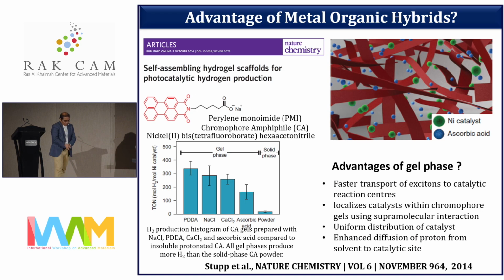So this is the first paper by Samuel Stupp's group, which really asked our group to think differently. This is the perylene chromophore, connected to amphiphile-type molecules, with a hydrophilic head and the pi chromophore. When it self-assembles, it forms a supramolecular polymer, and eventually crosslinks to form a gel. This acts as the light harvesting moiety, and when connected this way, the exciton migration is very efficient, enabling faster transport of the exciton to the catalytic site.